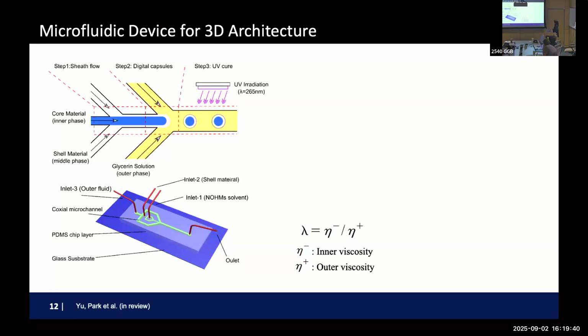And the clear liquid here is a UV curable polymer. So you have a microfluidic device making droplet-in-droplet. And then we UV cure, only curing the shell material, which is porous to CO2. And then this porous material, now you have a combination of a liquid solvent still inside, intact, with a large surface area per unit volume, with the shell material letting gas in and out.